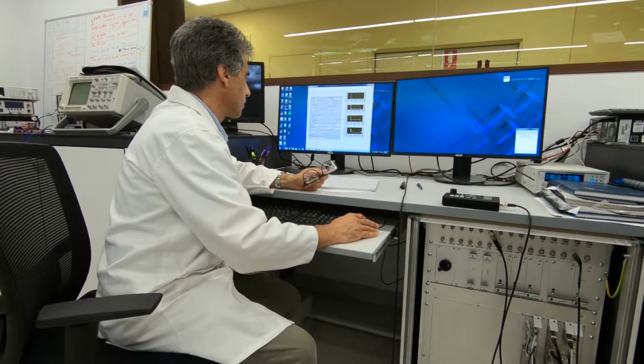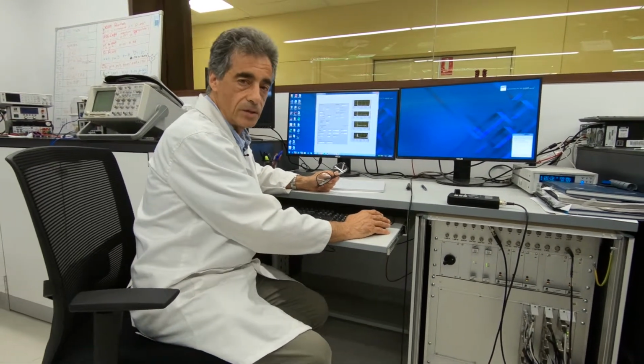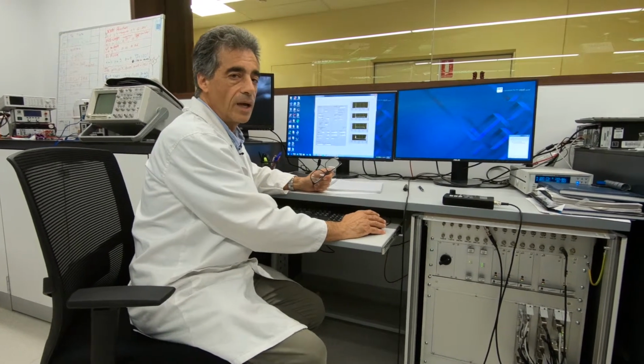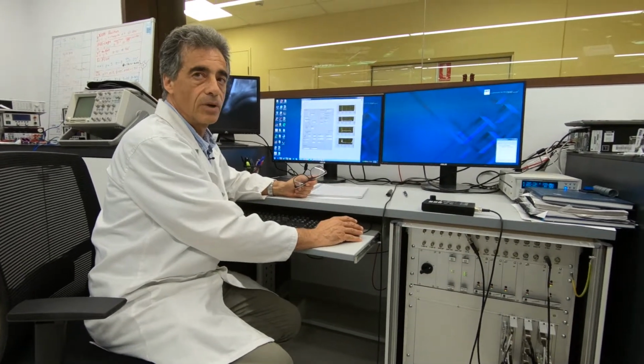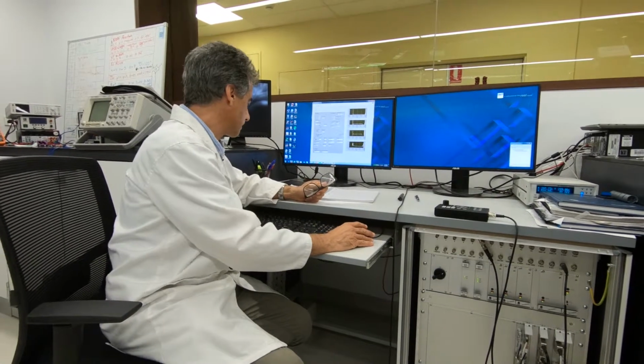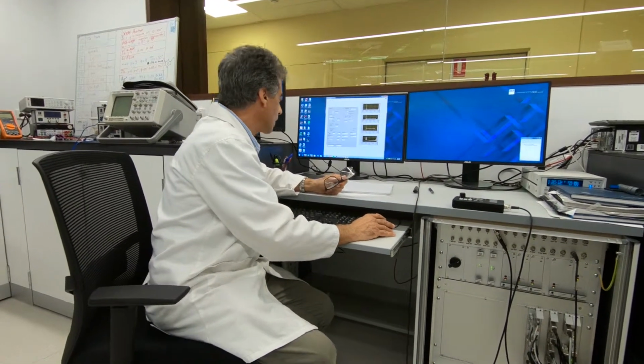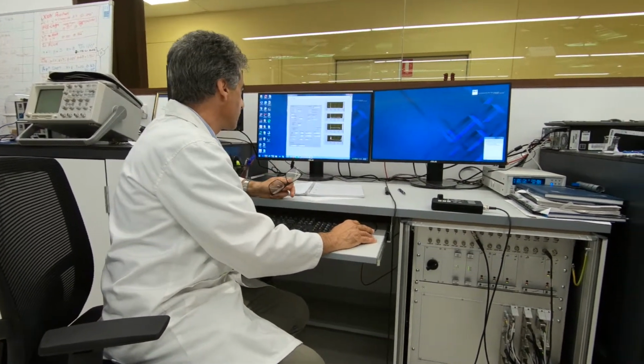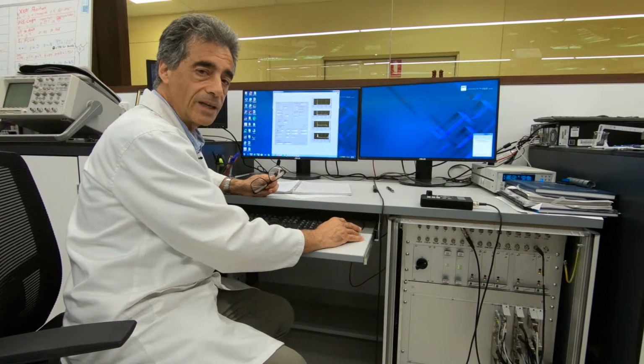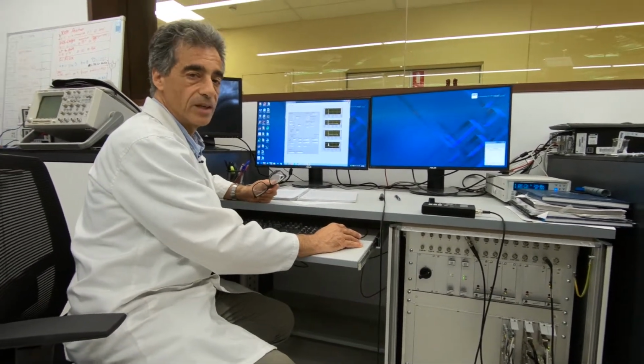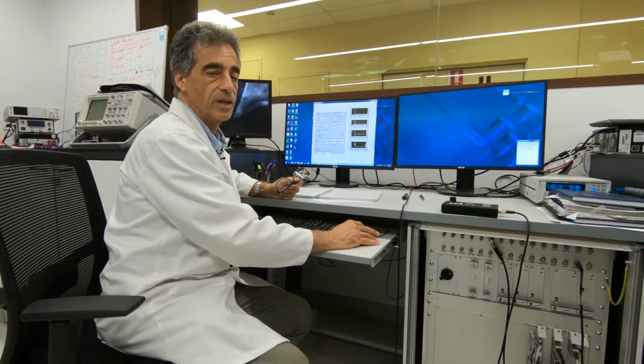That will keep the temperature at that level for 5–10 minutes. Once we have that for 5–10 minutes, we are nearly sure that the graphene is formed. We need to keep an eye on the vacuum so that it does not exceed 5×10^-9, in order to have the perfect, cleanest graphene surface.